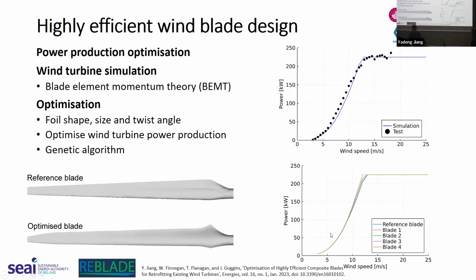After some optimization studies, we obtained 4 different blades, and the reference one is the lowest one. This is the power curve, and blade 4, which contains different foils, different sizes, and different twist angles, has better power production efficiency. Overall, it will have roughly 3 to 4% more annual power production. And these figures show the shape comparison between the reference blade and the optimized blade.